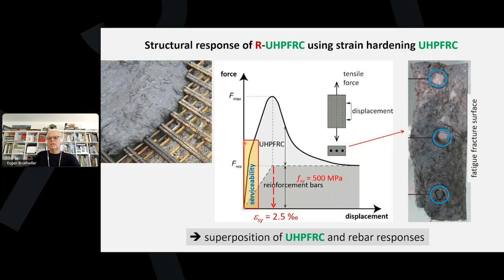Now, usually UHPFRC is enhanced by adding reinforcement bars. It is very economic to complement UHPFRC with steel rebars. On the right-hand side, you have a fatigue fracture surface, which means that we also studied the fatigue behavior of this material, including rebars.